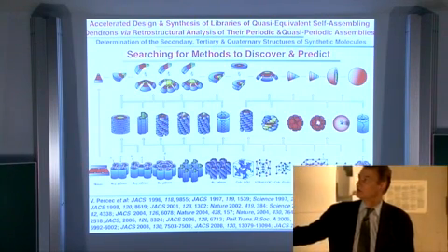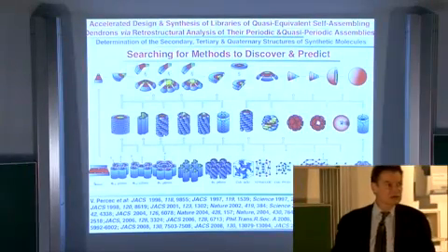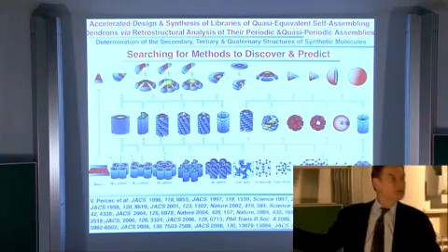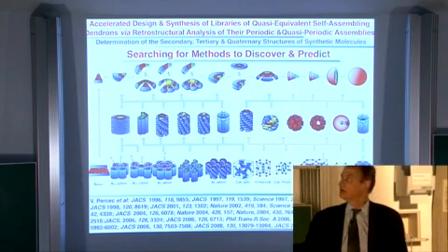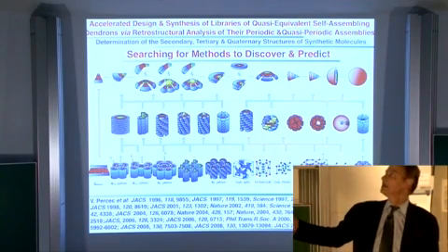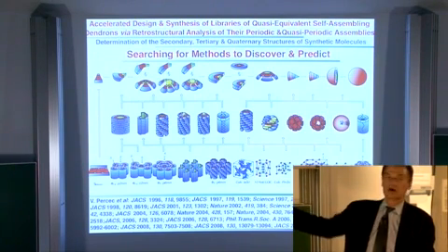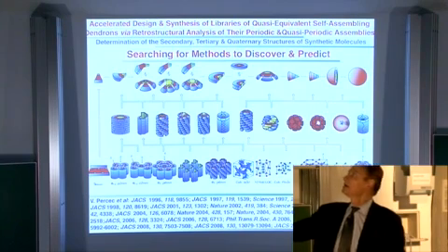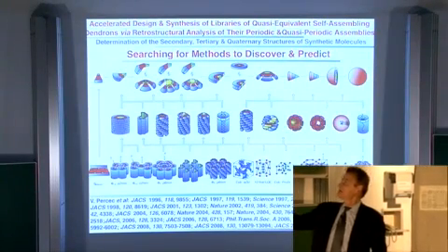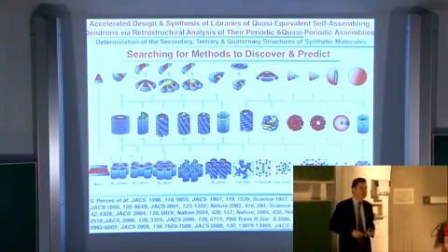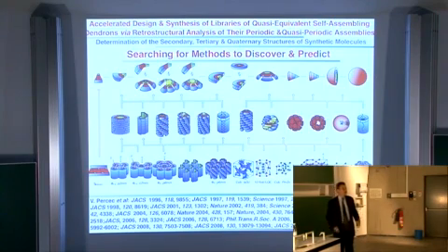That means if we solve this lattice and we know that it resembles this structure from here, and we have all the structural information, including densities, lattice dimension, and so on and so forth, we can calculate how many globular objects are in this lattice, how large is the globular object, and we can determine the conformation of the dendritic building block that is assembling into this globular object, and that's the equivalent of the secondary structure of the dendritic molecule, and this is the tertiary structure, and that's a quaternary structure. Okay?